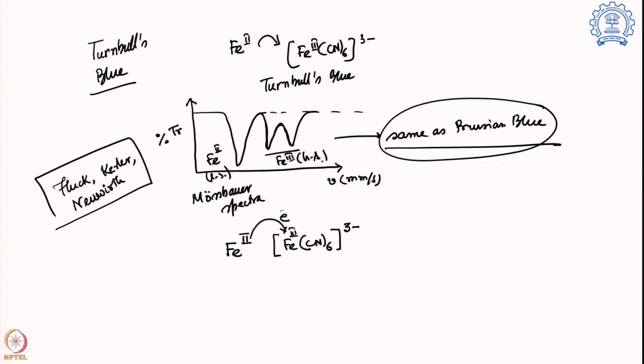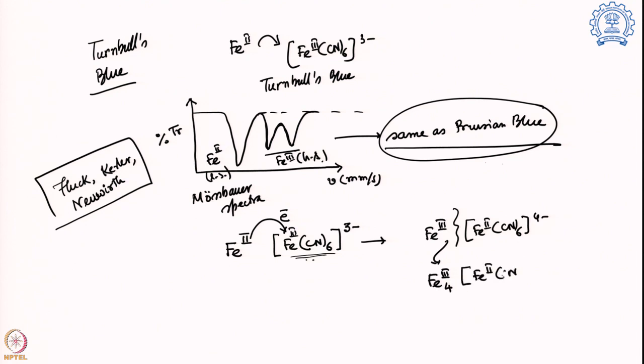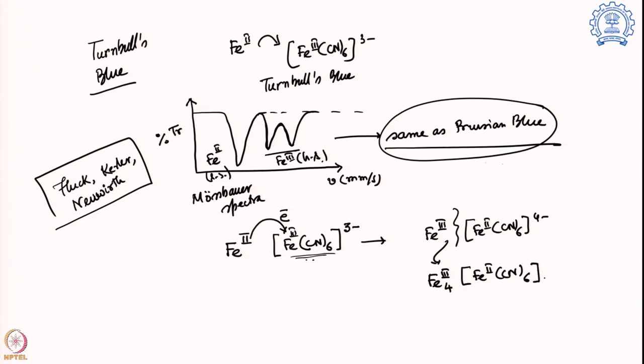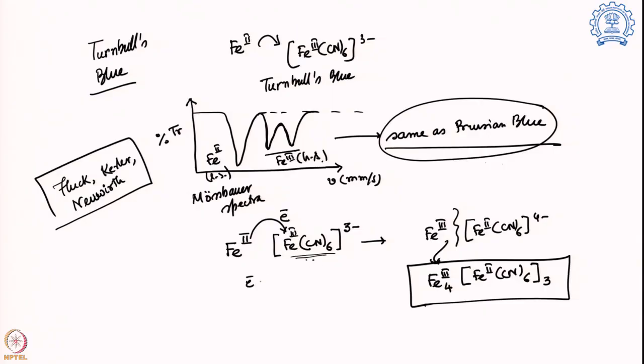One electron is transferred from the outer ion to the inner complex ion iron, and they produce iron 3 on the outside and Fe(CN)6 4 minus on the inside, which further coordinate and give us the complex, and that is why we are getting the same Mössbauer spectra. So it is showing that although Turnbull's blue is reacted in a different way, at the end it is going to showcase the similar structure because there is an electron exchange step happening. And Mössbauer spectra actually gave us the first hint that it is happening in this particular molecule.